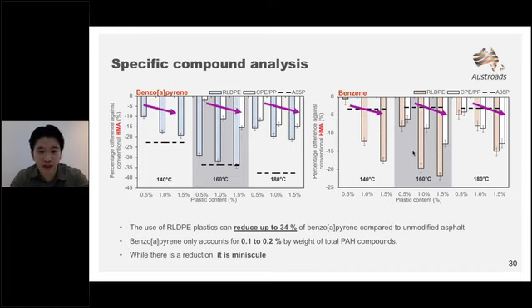With increasing plastic content, we see an increase in reduction for both benzo[a]pyrene and benzene levels. Specifically at 160 degrees Celsius in gray, we see the largest reduction of these carcinogens by about 40% and about 20% using recycled LDPE and CPE. On the other hand, benzene levels were reduced by up to 20 and about 15% as well on the right-hand side. And it's important to remember that benzene and benzo[a]pyrene only account for about 0.1 to 0.4% of the total emitted compounds.